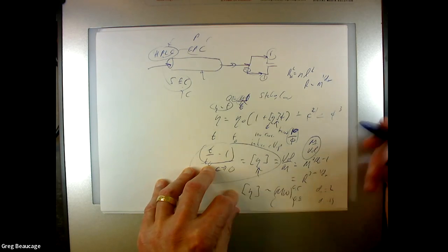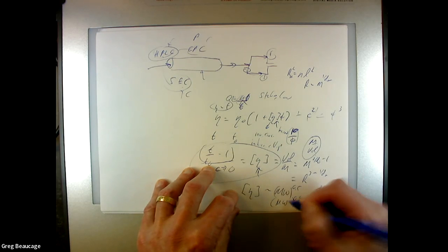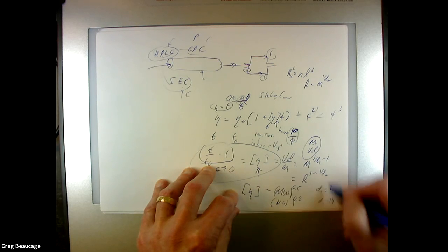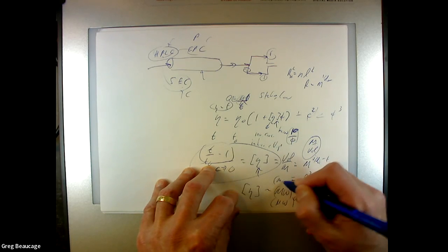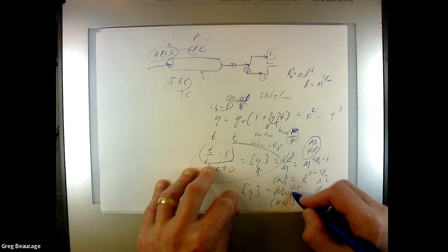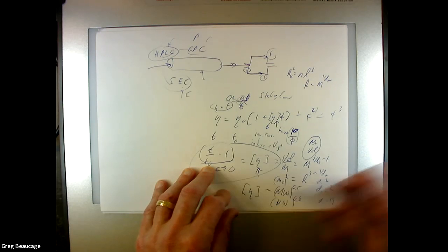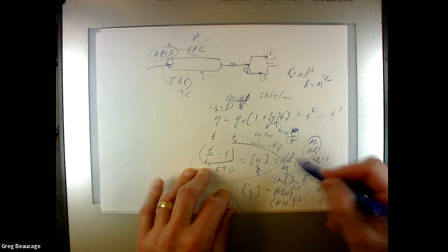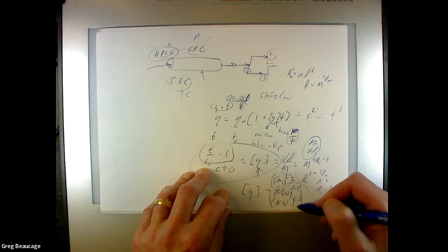Like 4/5 is 8/10, 0.8. And if dF is 1 for a rod, it's 2. You get quite a wide range: a rod to a Gaussian coil is from 2 to 0.5 for this thing. So you definitely can tell a rod. Telling these two is a little bit more tenuous.